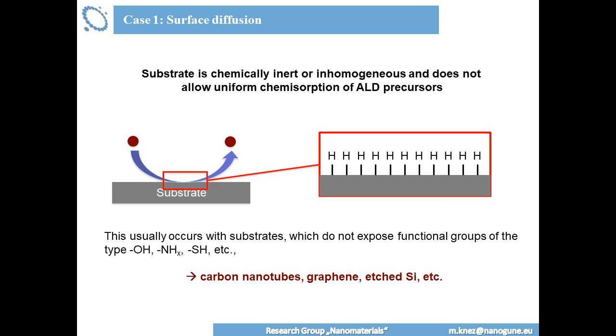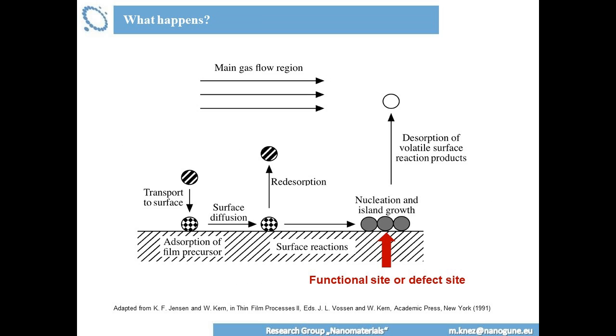In normal cases, you will not have a completely inert surface, you will have defects. And what happens there is, you have a precursor coming to the surface, it may physisorb, it will diffuse. In the ideal case, it will desorb again. So this is the ideal situation. But in the non-ideal situation, it will diffuse further. It will come to a certain point where you have a functional site, the defect site, and it will nucleate. And from then on, you have your nucleation spot being the substrate for your ALD.